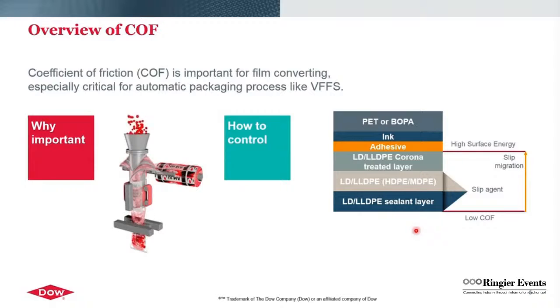However, there are cases where the COF initially achieved does not remain consistent. The COF value of a packaging film has been observed to vary. One possible reason is that the slip additive may migrate inwards towards the adhesive that has high surface energy, especially with the use of solvent-free adhesives. This phenomenon of COF variation may not be observed immediately after the laminate is produced. The result is unstable COF or poor runnability on converting and packaging machines.